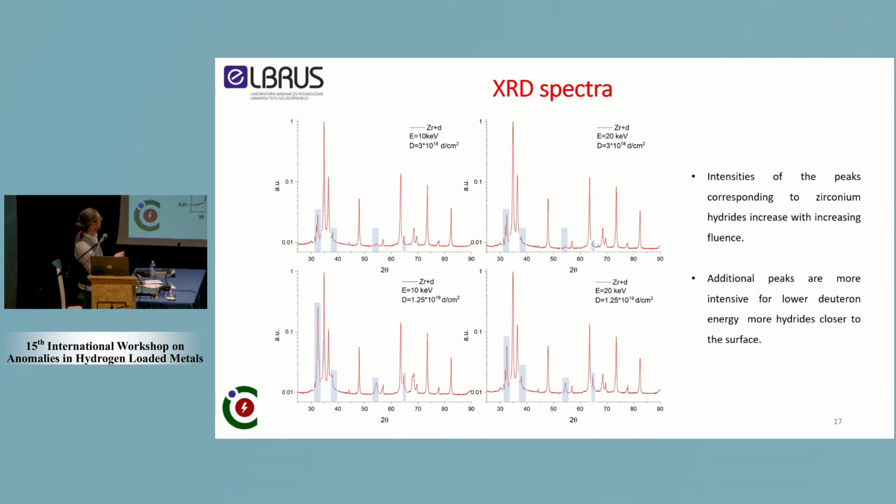However, when we look at the same energy with different fluences, the size of the peak is greatly influenced. So we have all these peaks that are mostly influenced by the fluence, rather than the energy of the incident beam. So it gives us how the beam is interacting and modifying the crystal structure on the surface.